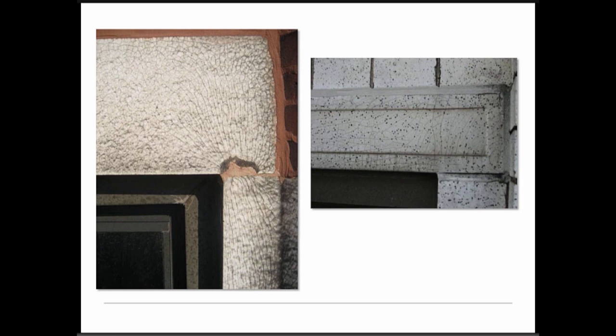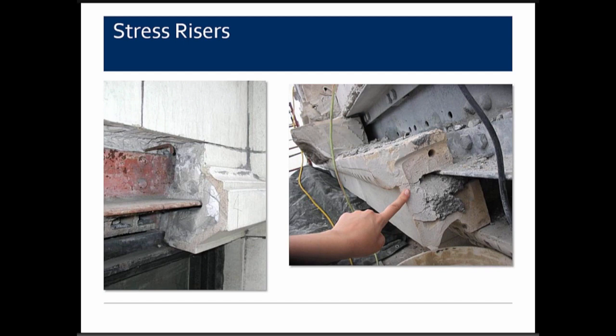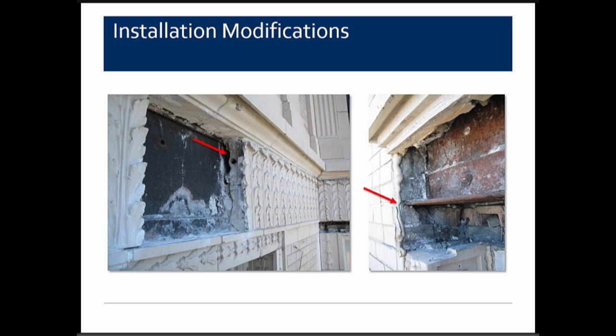Crazing at the corner of a pier top indicates stress where the lintel sits on the jamb unit. The bearing condition of the terracotta unit on the structure also matters — a unit notched out either in manufacturing or by the contractor with minimal bearing back on the angle creates a weak spot. The crack runs to the face of the unit, and units above projecting also cause cracking in units below due to insufficient support.